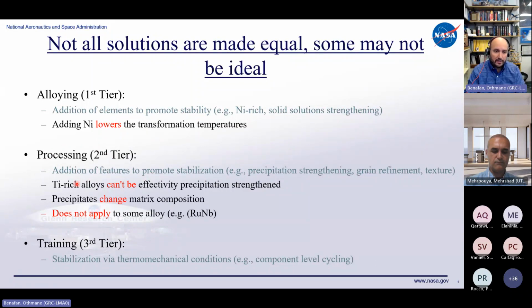But in the case if you have a titanium-rich alloy, nickel titanium, for example, or nickel titanium hafnium or anything, if it's on the titanium-rich side, you cannot effectively precipitate strengthen. You can precipitate the bad phases that will hurt the device or the alloy, but they're not very effective for precipitation strengthening. Precipitates also change the matrix composition. So when you pull the matrix out and the precipitates happen to be nickel-rich, you remove nickel from the matrix, effectively making the matrix a different composition, and therefore your temperatures can change.